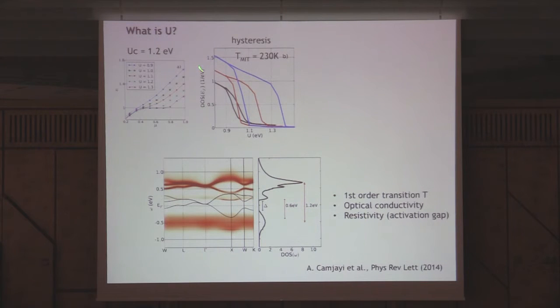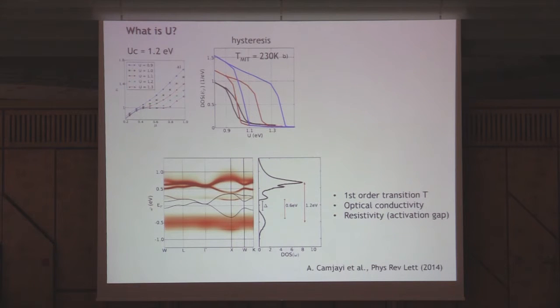And moreover, with these values of U, we can get the interacting band structure, the Mott gap is open there, and we can get all the gaps, the transport gap, delta, and the optical gap there, and that fit very nicely with available transport and optical conductivity experiments. So with all this, I tried to convince an experimental friend that he has to be a friend, because otherwise he will never convince somebody to do a pressure experiment on single crystals that were fabricated in Nantes.